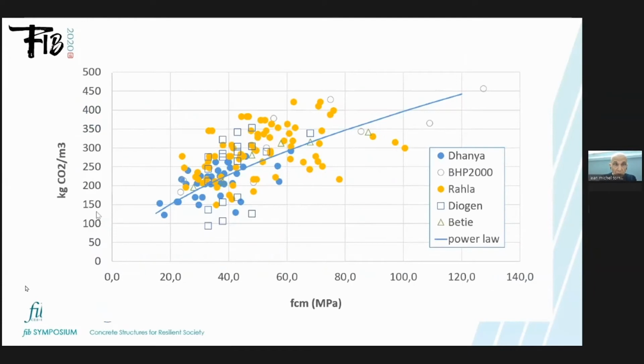Here I place several mix designs and I have evaluated the CO2 impact. You see it's very low and only some of the concretes are able to obtain this result. So it's not easy to obtain this level. And also there are of course some problems due to the evolution of the strength in time. And so there is an impact on the way you build what you want to build.